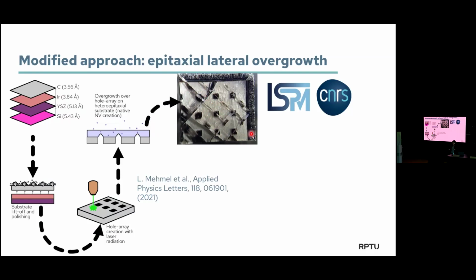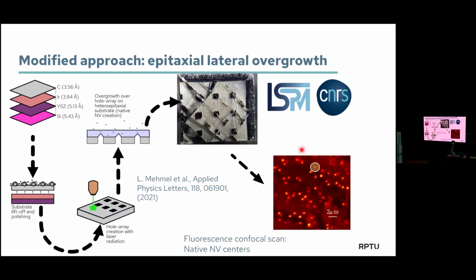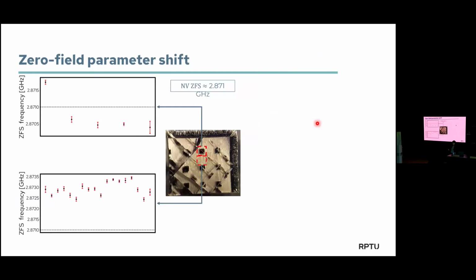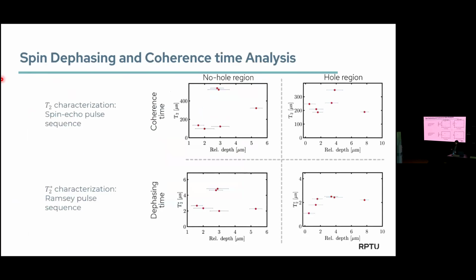And now we have looked into the samples again. We also see single NV centers, so it's a highly pure material. And we have been looking into the zero field splitting, so the position where we see the ODMR without any additional fields. And we see that when you are in these holes, you are closer to the ideal position than outside the hole. So it's really this growth in free air, so to speak, that allows the dislocation density to reduce and the stress goes down. And there we are still looking into this at the moment.